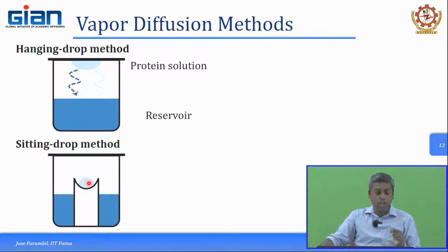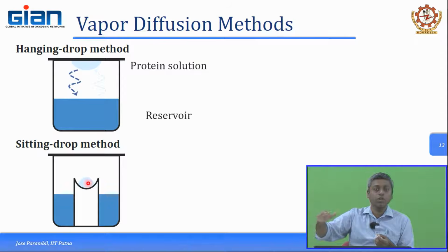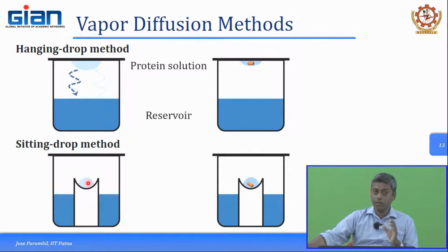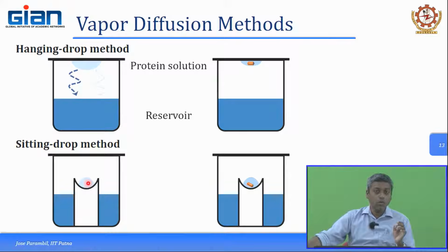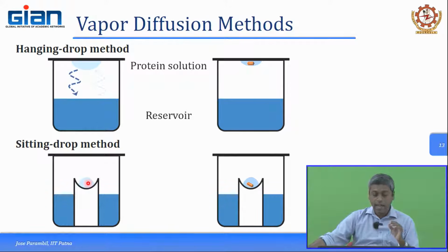So, overall the volume of the drop sitting over there with the protein would keep on decreasing. As the volume of the protein solution decreases, what happens to the protein concentration? It would increase. Over time the protein concentration would increase, reach the nucleation zone, and start nucleating, and small crystals would be forming there. So, this is a very slow but effective way of controlling the diffusion or the evaporation process, leading to a nucleation which can eventually produce the protein crystal.